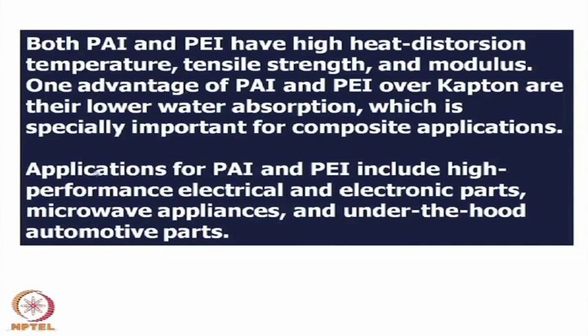Applications of polyamide-imide and polyetherimide include high-performance electrical and electronic parts, where moisture absorption must be minimized because it strongly affects electrical resistance properties. PAI and PEI show further lower water absorption than Kapton, making them better polymers for electrical insulation applications. They are also suitable for microwave appliances and under-the-hood automotive parts.